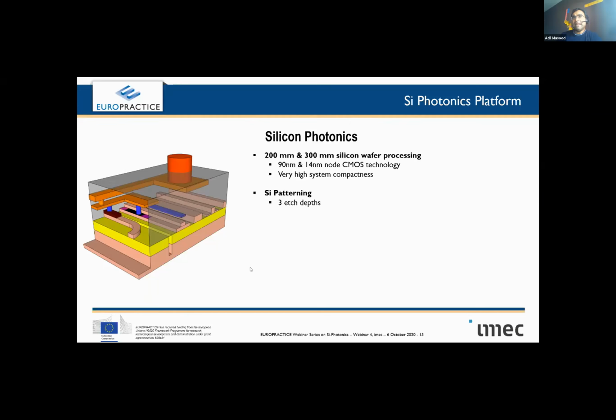Now, what is offered through MPW? There are 3 levels of silicon patterning, which means if you see that this thickness of SOI is 220 nanometer, then it can be etched all the way, or partially down to 70 nanometer, or down to 150 nanometer. So that gives more variation in making different kinds of waveguide geometries. There are 8 different kinds of implant options available for silicon in the silicon platform. So that means that you can really change the electrical properties and really use silicon as a semiconductor material, what it is meant to be, by doping it in many different variations and acquire whatever application you are aiming for. And then there is an epitaxial germanium growth, as shown here, that allows fabrication of modulators and photodetectors. And then the backend is CMOS compatible. It is a CMOS backend basically. So that eases packaging and assembly.